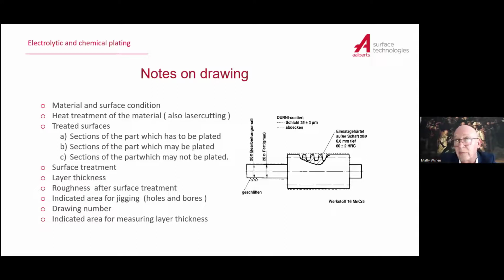For instance, you have a part which is partly covered with mill scale, and where the part is milled completely free. These are things which we have to know. We have to know if the material is heat treated. Also, for instance, laser cutting. When you make stainless steel parts by laser cutting, on the edge of your stainless steel you will form chrome carbides. These chrome carbides will give you bad adhesion when you plate them. The problem is you don't see them. So if you laser cut your materials, please notify us or put it on the drawing, because then we know we have to etch it or treat it, or aluminum oxide blasting or something like that, to make sure that the chrome carbides on those parts are gone.